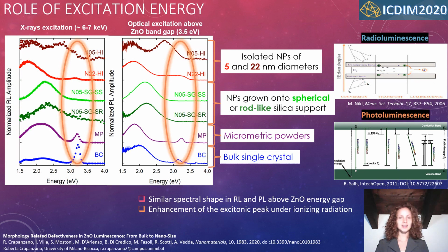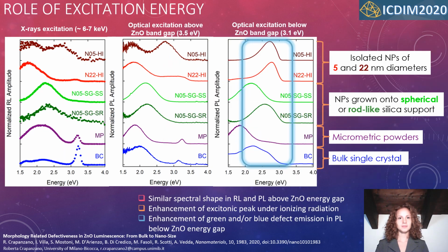The greatest difference is the intensity of the excitonic peak, which is boosted under ionizing radiation. This result can be due to the enormous number of carriers generated in the radioluminescence mechanism, while in photoluminescence, one absorbed photon generates only one electron-hole pair, leading to a lower probability of exciton recombination.